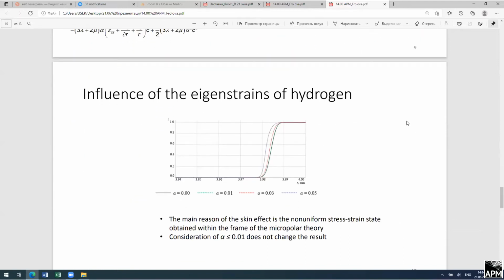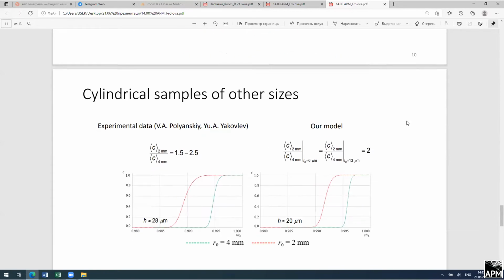Also, we don't have exact values of linear expansion coefficient of hydrogen, and therefore here we used different values and analyzed the influence of swelling strains of hydrogen on the result. So first of all, we can see that the main reason of the skin effect is still non-uniform stress strain state obtained within the frame of the micropolar theory, not swelling strains of hydrogen. However, higher values of linear expansion coefficient can lead to deeper penetration of hydrogen inside the material.